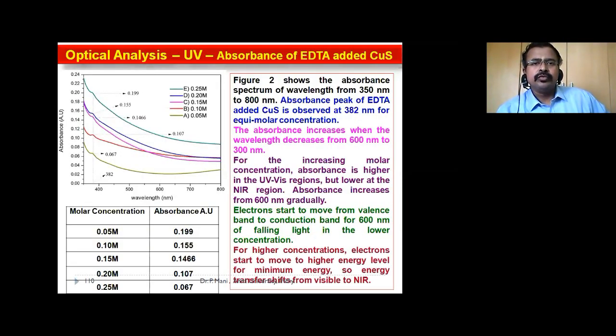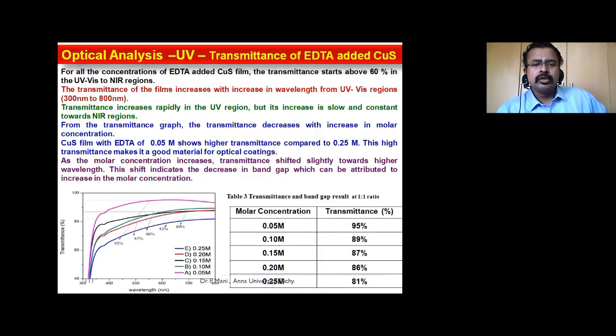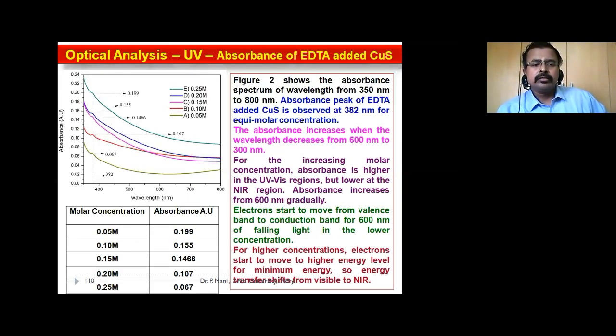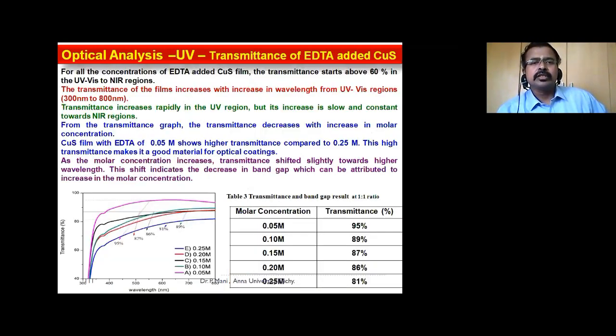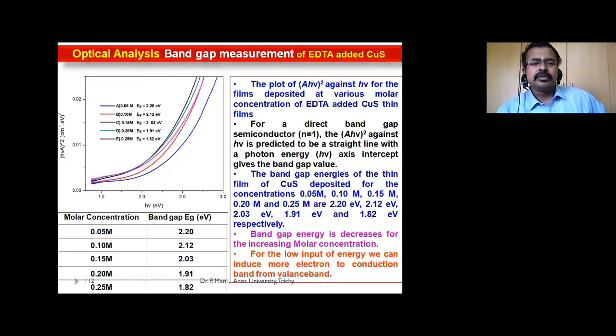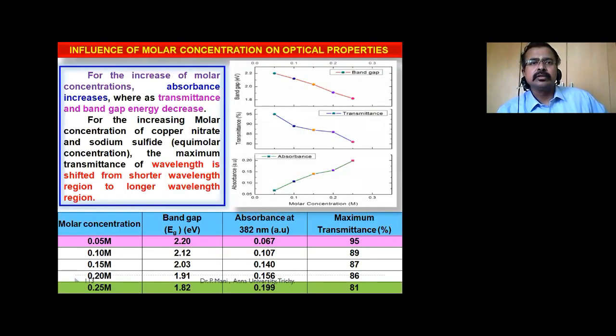Optical analysis, UV absorbance is showing 0.067 to 0.199 arbitrary unit absorptions for various molar concentrations, and transmittance ranges between 81% to 95%. Band gap is ranging between 1.8 to 2.20 for this EDTA added copper sulfide solution. The influence of molar concentration on optical properties is ranging here.